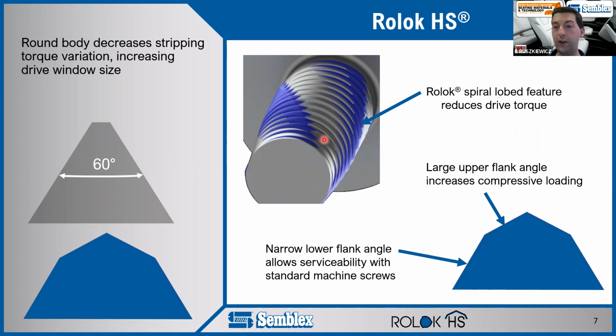Finally, is our torque controlling feature to make sure we have a good gap between that drive torque and the failure torque. We chose to use the Rolok spiral lobes, which is where the Rolok HS name comes from. It simply is Rolok for high-strength steels. The reason we went with the Rolok spirals instead of a trilobular body or a non-uniform cross-section is that we get better stripping torque performance out of a round body fastener. That was going to be very important for these high-strength steels.